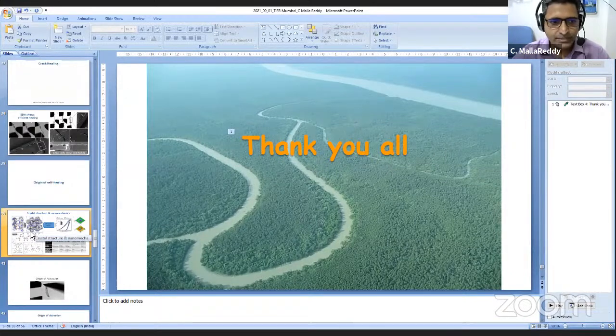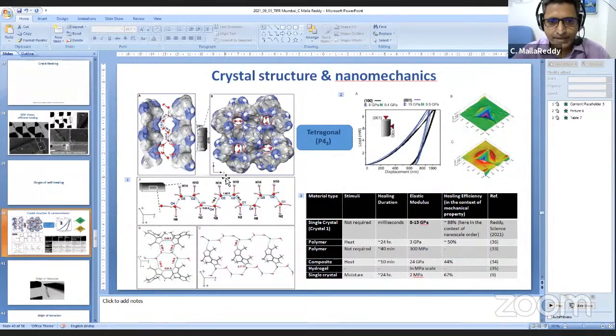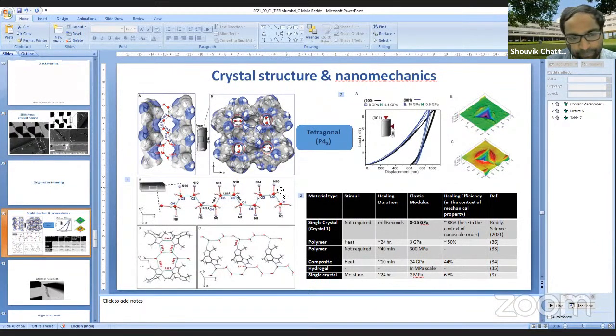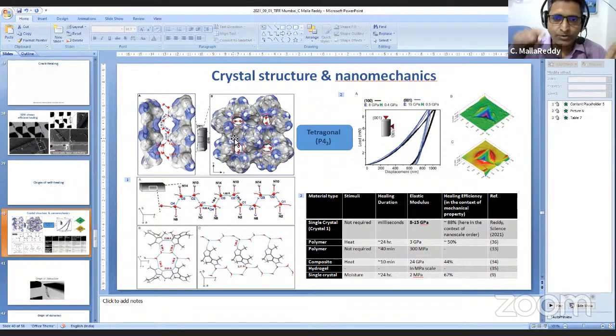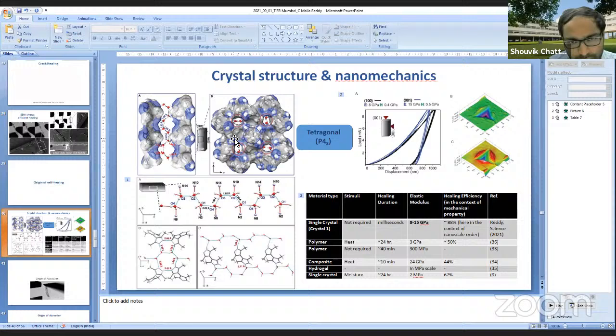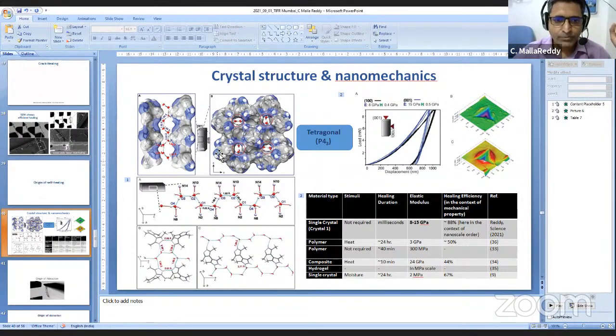For example, if you look at this, can you see this now? Yeah. So this is the plane that we are talking about. Now you're looking along the needle direction of the crystal, the long axis of the crystal. And when you break it, this is the surface you would normally see. And if you look from the other axis, the 001 is the top one. So this surface is basically 001. So you're looking along the C axis, and this is the surface that you open up when you break it here.